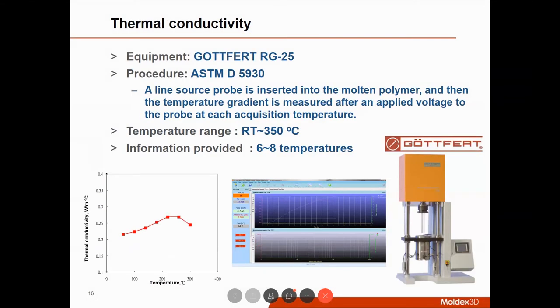As for thermal conductivity, we use the RG25 under procedure ASTM D5930. The polymer will be put in this chamber, and with a line source probe, we'll insert it into the molten polymer and then apply a certain voltage to the probe and record the whole temperature gradient as shown here. With the temperature range from room temperature to 350 degrees Celsius, we will be able